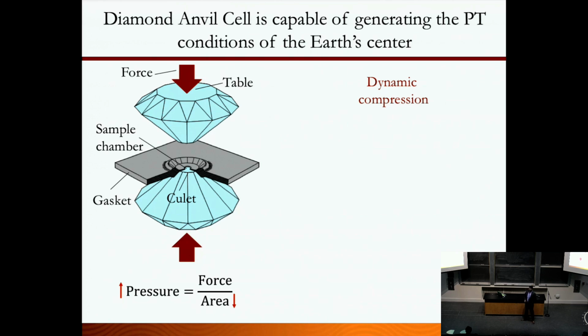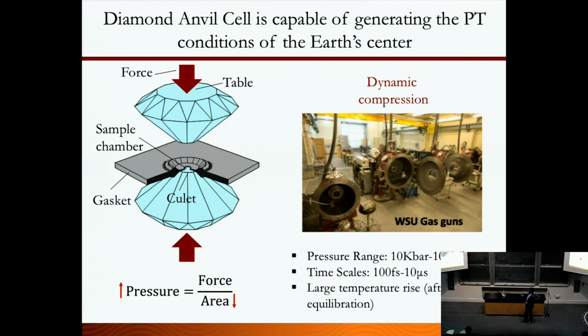There's another way of generating really high pressures, which is dynamic compression. You can use a shock wave. You can subject the material to a shock wave and generate really high pressures. You've seen these, they're gas guns. You fire a bullet at a metal steel target and create a shock wave. This is from my previous institute where I did my PhD. They have these huge guns to generate really high pressures and study materials under extreme conditions.